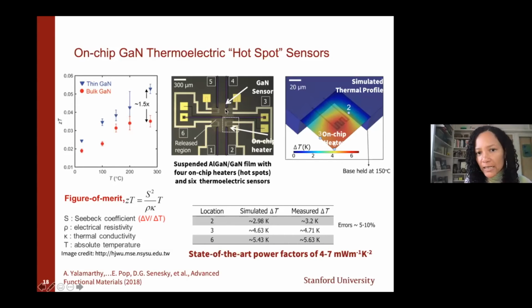So that is the hot side of the thermoelectric device, and then you have the cold side on the substrate. So using the silicon substrate as a heat sink, you can have a delta T across the thermoelectric sensor. And then we have these little resistive heaters. These are our hot source here. And so we're creating a delta T across the two-dimensional electron gas, and we're measuring fairly high power factors on the order of 4 to 7 milliwatts per meter Kelvin squared.